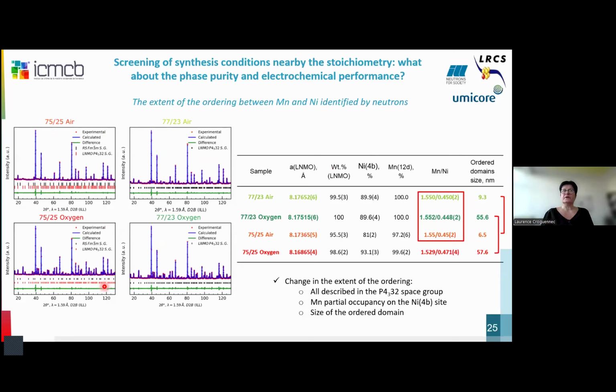So if we go further into the structure of these materials, I just put this X-ray diffraction pattern to convince you that the results were of good quality, but we will focus really on these results here. If we consider the manganese-rich material, whatever the atmosphere we use to prepare these materials, it does not change the structure so much. You can see that the cell parameters are very similar, and I would say the distribution among the two different sites also.